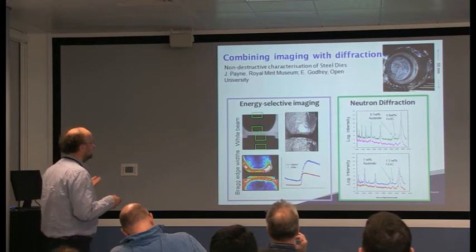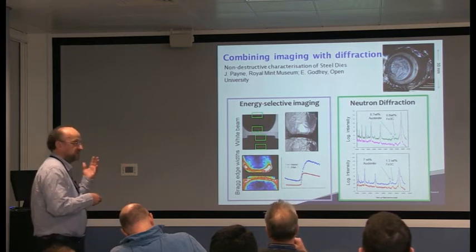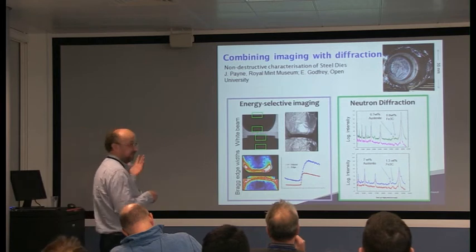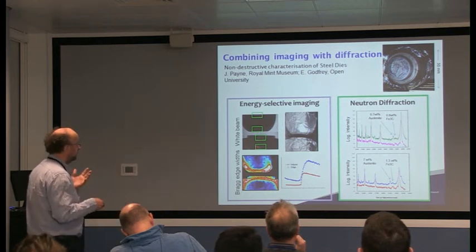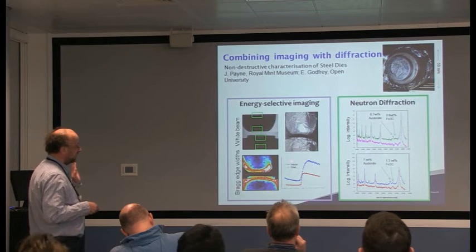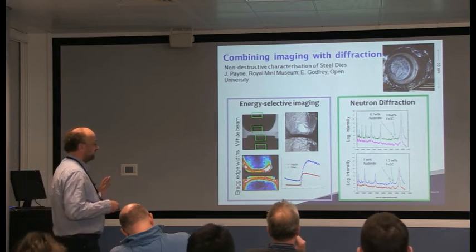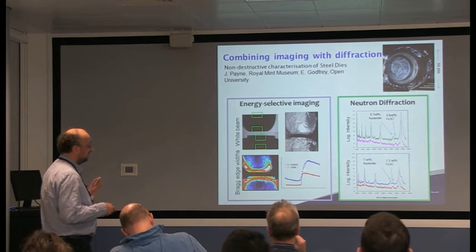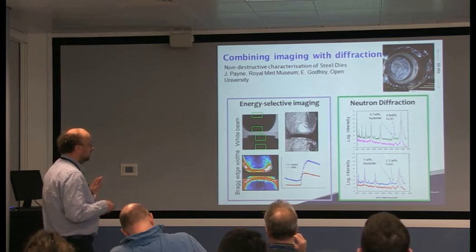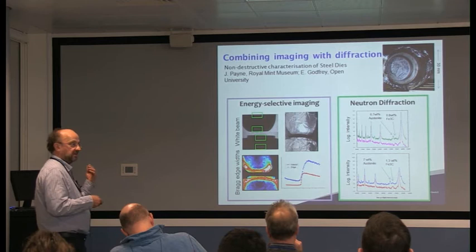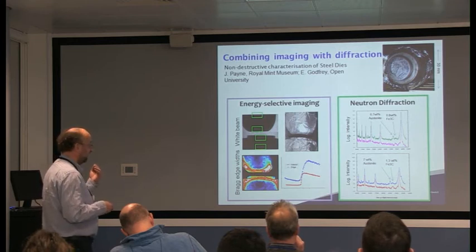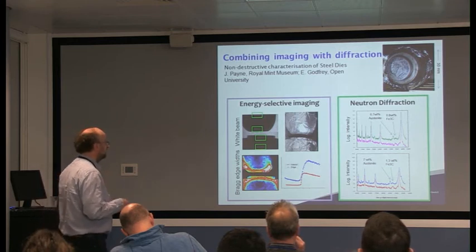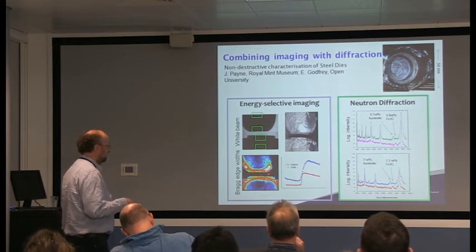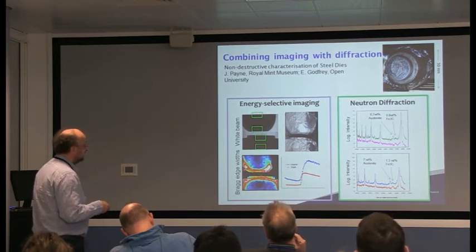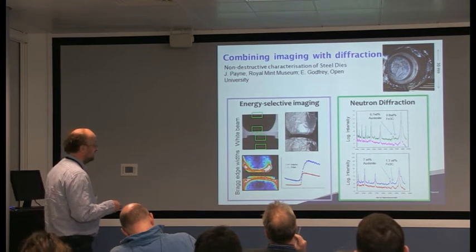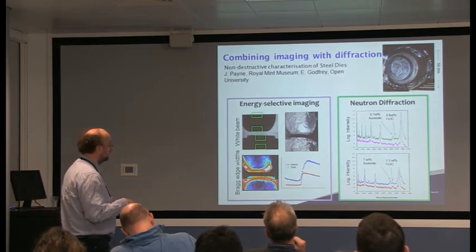And what we see is that with wide beam techniques, it's pretty hopeless and we don't get much information out of it. But as soon as we measure as a function of energy and analyze the Bragg edge positions and the width of the Bragg edges, we start to see phase transitions from the martensitic phases on the outer skin to ferritic phases in the interior. So that's what we want to analyze.